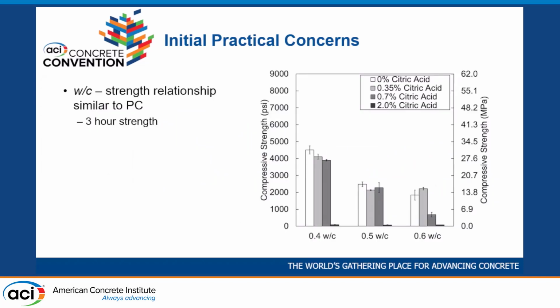Another thing we've looked at is just compressive strengths. That's obviously really important for structural design. So we've done a bunch of testing with different citric acid dosages, different water cement ratios. If we use 0.35% citric acid and it's room temperature, and we use a 0.4 water cement ratio, we can exceed 4,000 psi in 3 hours. So that's generally what we're aiming for, because this kind of maximizes the benefits of this cement, the really, really high early strength.